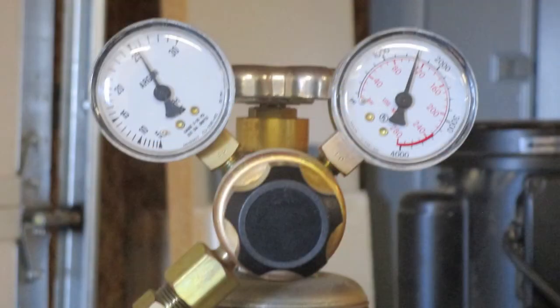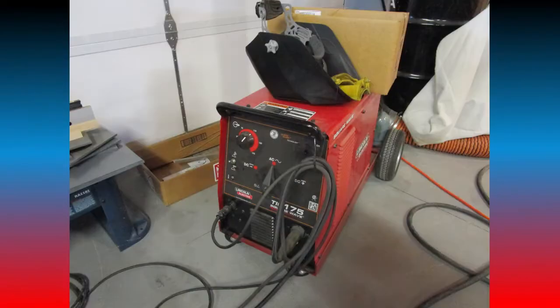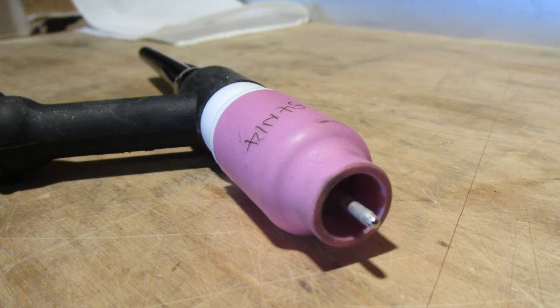Argon is the shielding gas used for aluminum. The pressure used here is around 27 pounds, which provides adequate gas flow through the gas lens and nozzle. Make sure there are no air currents present that will blow away the shielding gas. Air conditioners, fans, humidifiers, and heaters can cause problems. Welding in still air is best. A 3/32-inch tungsten electrode is used here with a 3/8-inch protrusion from the nozzle. A close-up of the 17 series torch, electrode, and nozzle are shown as an example. Use what works best for your specific welding conditions.